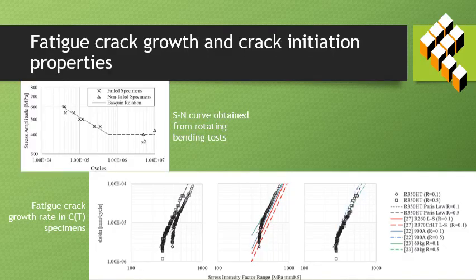For this, we conducted rotating bending tests to characterize resistance of R350-HT against crack initiation, and fatigue crack growth rate tests using CT specimens in order to characterize the resistance against crack growth. These have been conducted at different load ratios.